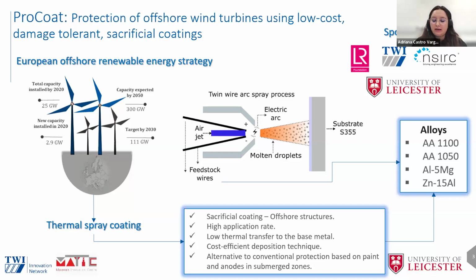So basically, it's a good alternative to replace the conventional protection based on paint and anodes in submerged zones. So here you can see in the figure schematically the process. The twin wire arc process consists of forcing two electrically charged wires to establish an electric arc.